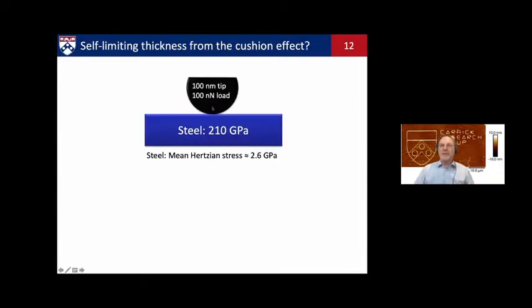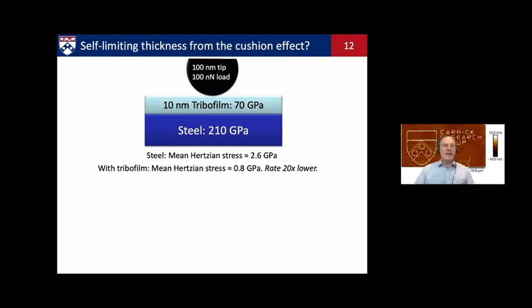So let's think about what this means for the growth of the film. If I calculate the stress I would get for a tip on steel at 100 nanonewtons load, I'd get about 2.6 gigapascals for my AFM tip. If I now let the film grow to about 10 nanometers, using literature values for ZDDP tribofilms, there's a range, but say around 70 gigapascals is a reasonable value. After just 10 nanometers of growth, the mean Hertzian stress, according to continuum mechanics, has dropped to about 0.8 gigapascals, dropped by a factor of 3. Now remember, the growth rate depends exponentially on the stress. So that translates to a 20 times lower growth rate of this film.